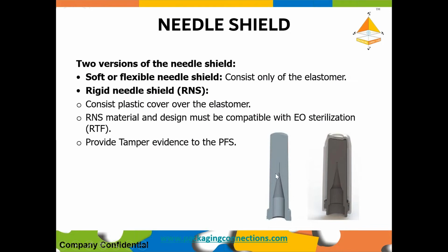These two, one could be a rigid needle shield or a soft, flexible needle shield, elastomer. It's easier to pull the soft one, but I think the rigid is better from the point of view of damage and is compatible with ethylene oxide. So it depends again on the end use, what you're looking for.